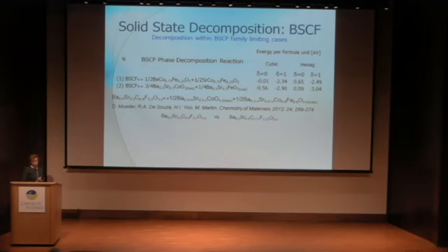And then we wrote a whole bunch of different decomposition reactions. What we found with Schottky-like disorder and clustering effect means that cations are not highly ordered in the material. And if that's the case, you immediately come with an idea that it's probably possible to decompose these complex perovskites in other phases. And these two equations actually show that.